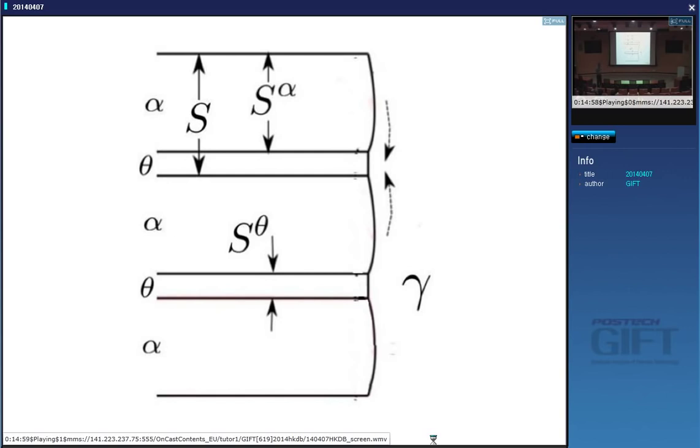Okay? So actually the diffusion this time is not occurring in the direction of growth. It's happening from here to here. Okay. This is the diffusion path. It's parallel to the transformation front. And the diffusion distance is determined by the interlamellar spacing. Right? So that diffusion distance is a constant.